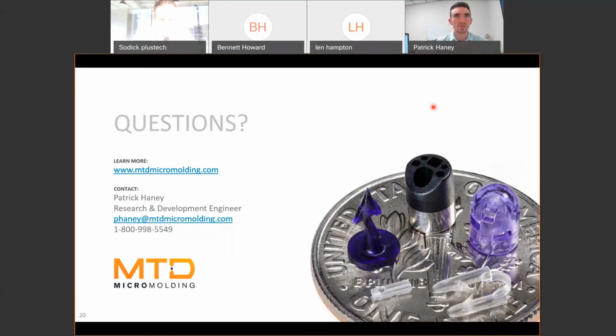I think another challenge with TPUs, especially the softer ones, or the more soft block you have in your polymer backbone, is that if you require an elevated mold temperature, which micromolding projects do quite a bit because we need to retain that heat within the polymer shot for as long as possible to keep the viscosity low so we can fill our thin features, soft block TPUs can be kind of challenging because when the mold opens, they're still quite malleable, right? So we have to use a number of tricks to prevent distortion or shrinkage or voids and things like that. But again, we see TPUs all the time, and we've had successes with TPUs, so it's not out of the realm of possibility.